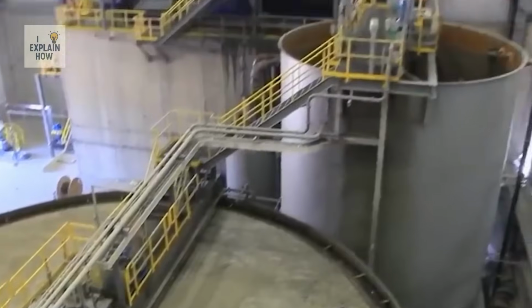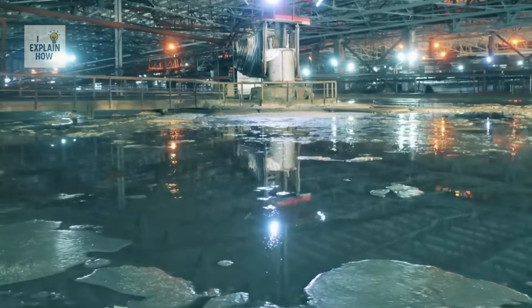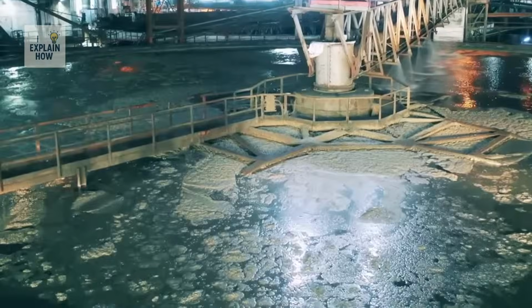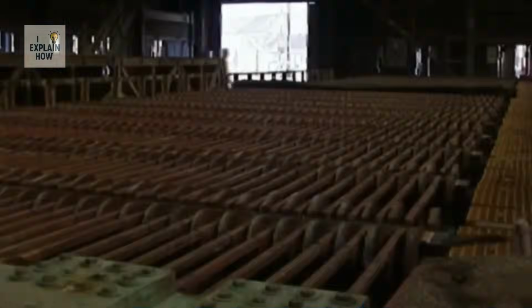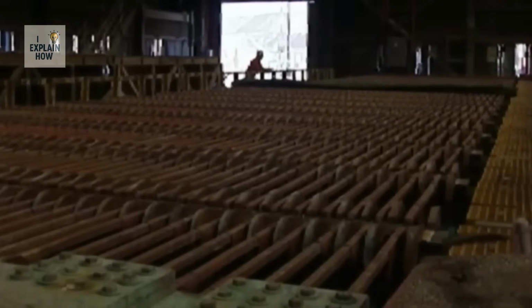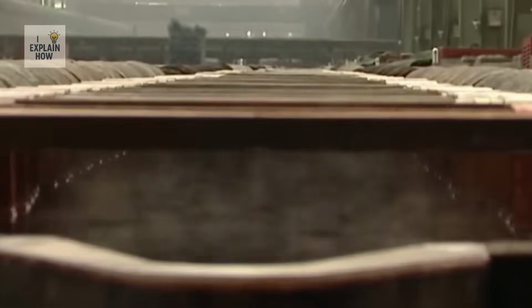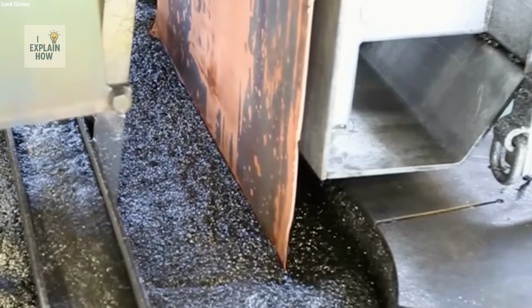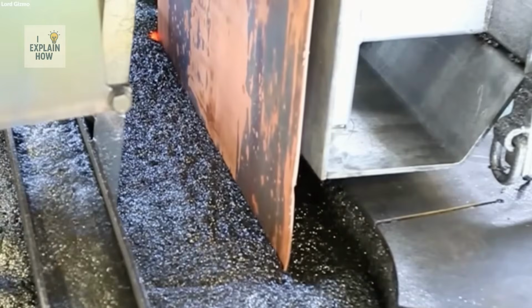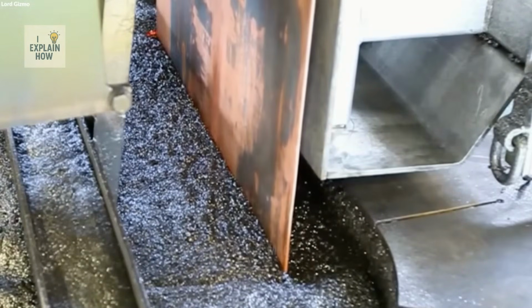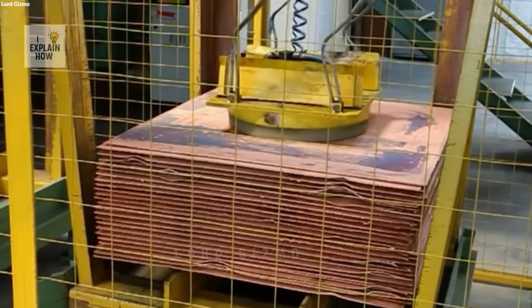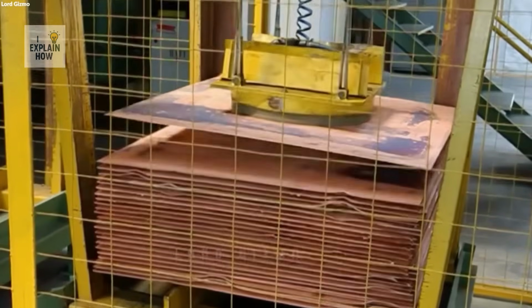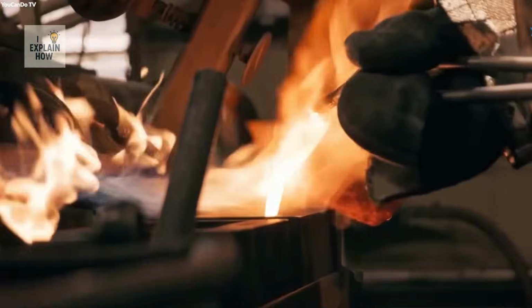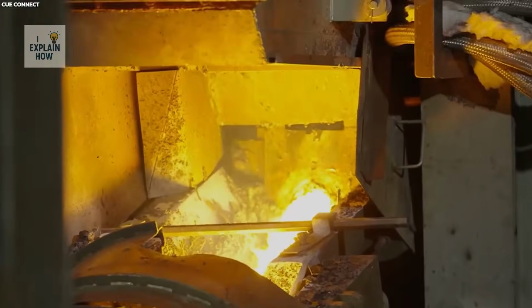In special channels, the copper solution comes into contact with an organic reagent that allows it to float on the surface. Next, an acid solution is added, which increases the concentration of copper and makes it electrically conductive. This liquid is then transferred to a series of large tanks containing thin copper plates called cathodes. Once an electric current is applied, copper ions gradually begin to deposit on the cathodes. In just 10 days, each plate reaches a thickness of about 2.5 centimeters. At this stage, the purity of the copper is close to 100%, which is essential for its use in the manufacture of electrical products.